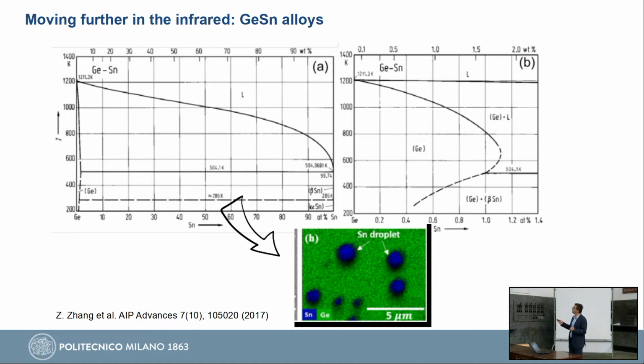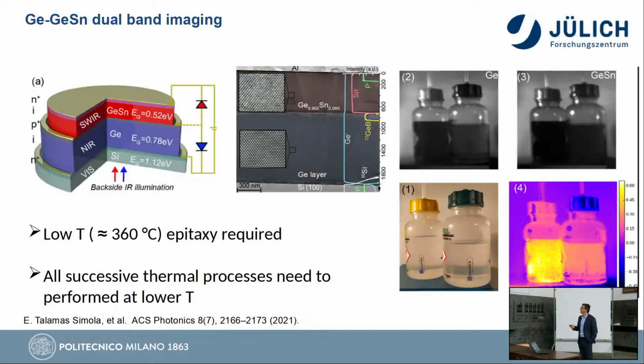If you go above this limit, in this region, what you obtain is two different phases. So you will have germanium and droplets of metallic tin forming. So it's no longer a material which can be used for fabricating optoelectronic or microelectronic devices. Only very recently has the technology evolved in such a way that this material can be realized. So this is an example of a collaboration we had with the Forschungszentrum in Jülich, and we repeated the same dual band thing, this time with germanium and germanium tin.